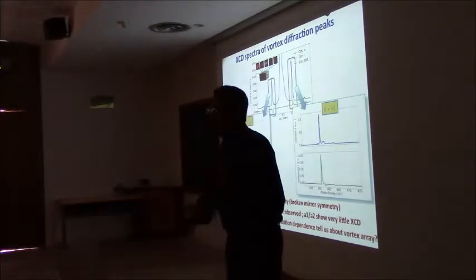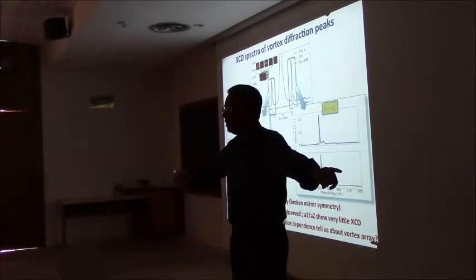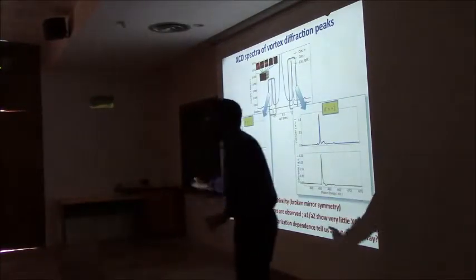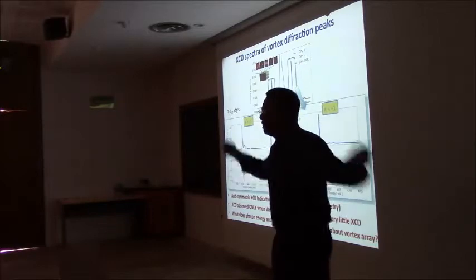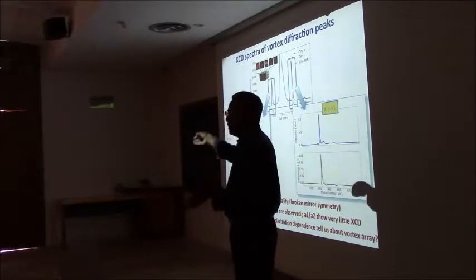A few points. When we have samples which have uniform polarization, we call that A1, A2 because the ferroelectric polarization is this way or this way in plane. With uniform polarization, we see no circular dichroism. Indeed, these samples already have, as I'm going to show you in a few minutes, a mixture of the uniform polarization and the vortex phase. And it seems like it doesn't even care about the uniform polarization because it is very resonant to that particular spacing of the vortex. That's the first part.